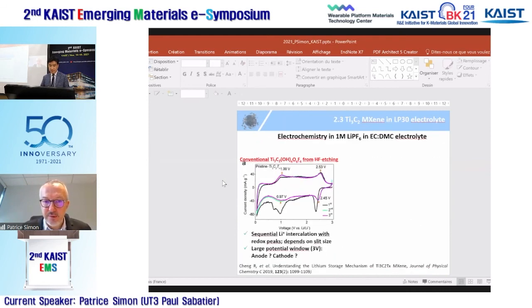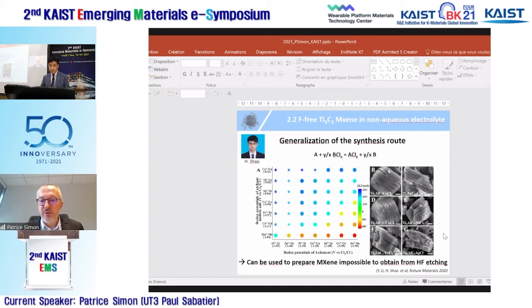Let me show. Yeah. So I show here some materials that we made. So we can prepare titanium nitride, titanium carbide, because obviously MXenes are carbide or nitride. But you can replace titanium with other metals. Sorry, there is an example with tantalum here. We did a couple of them, so I don't remember exactly. But yes, as long as you have a MAX phase available, and as long as the redox potential of your Lewis acid is higher than the redox potential of your A element, then yes, you can fully prepare these materials. You can remove zinc, you can remove aluminum, you can remove silicon and gallium, whatever you want. So this is really the beauty of this method, just by Gibbs energy coupling.